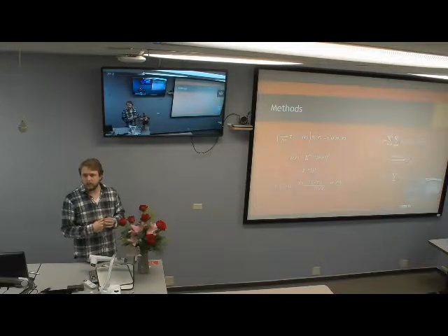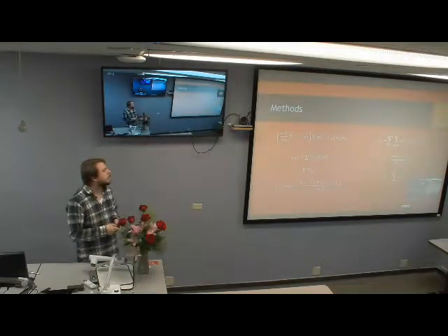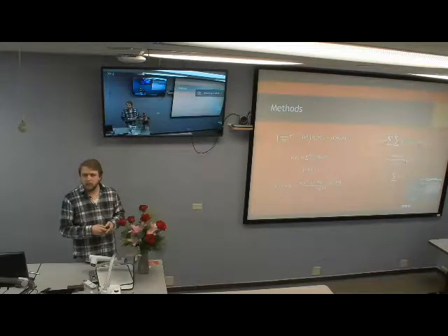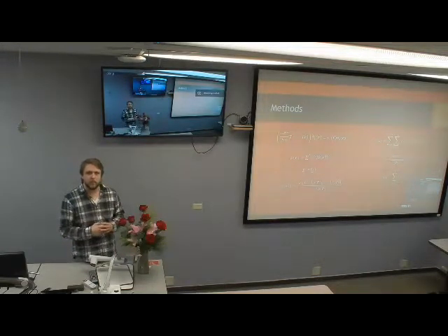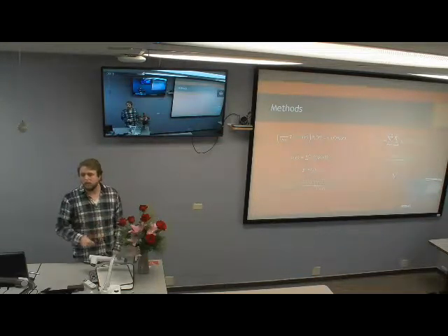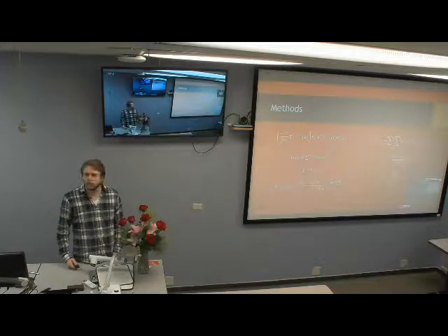Yes. Is it reasonable? What do you know about silicon? It doesn't seem completely unreasonable to me, but silicon is known to not really emit light. We say it's not a direct band gap semiconductor, so actually indirect transitions would be not optically active. Okay. All right. More questions to Nathan? If no, thank you once again.